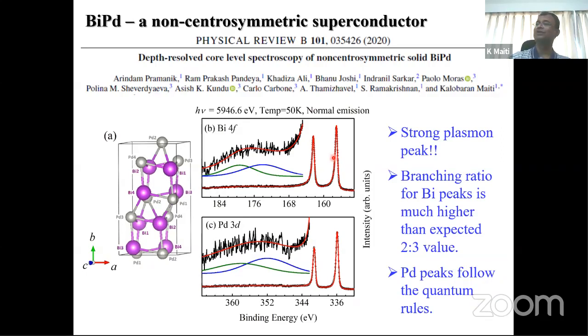Now you can actually change the probing depth by changing the emission angle. If you have normal emission of electrons, that has the highest probing depth, and if you have grazing emission, then the probing depth is much lower. That's the game that we play to find out surface and bulk electronic structures. Here we see that if you do a normal emission and a 60-degree angled emission, they look similar, as if the bulk and surface are somewhat similar in these materials. I wanted to look at the surface even in the core level, just to see, because the surface and bulk are expected to be different in this kind of material.